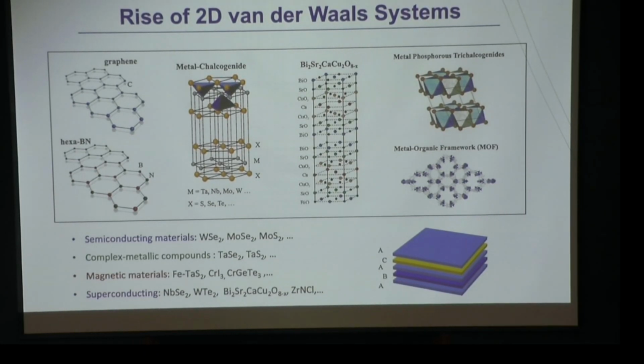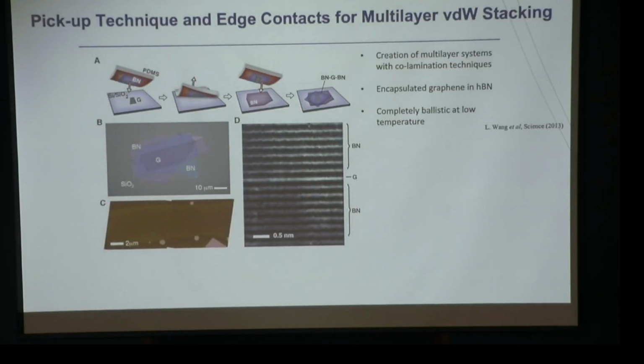And soon it turned out that this is not just PowerPoint generation; those kinds of examples can be made. Here is a good example from the collaboration I had at Columbia University, especially with Jim Hone's group. The method works something like this. You cleave the graphene crystal on the surface, and using sticky tape, or a stamp, you can pick it up. But then you can do this in a repeated way, such that you can make van der Waals stacks consisting of all different layers of materials. In this particular example, you start with boron nitride, pick up the graphene and another boron nitride, so you can see that graphene is sandwiched between the boron nitride layers.